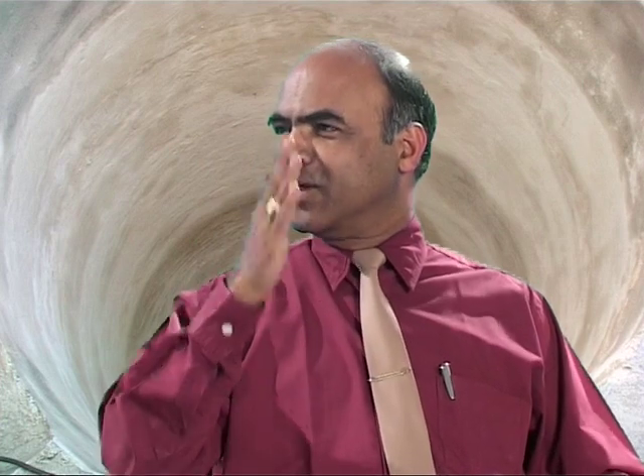Coil grouting cement, as the name says, grouting, means we are increasing the mechanical strength of the coil, because the coil, you know, is in the form of a spring, and by applying a cement on the coil you are making it in the form of a cylinder. So the first purpose is to increase the mechanical strength of the coil. And when we apply this cement, it should be very smooth on the coil, like a plaster on our wall, because if it is very smooth, then it will permit the vertical expansion of the refractory and will not give any damage to the coil.